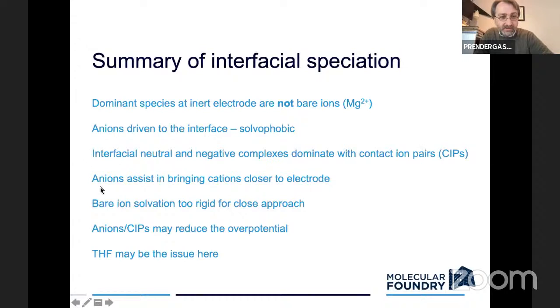But one thing you could draw from this is that the anions themselves are assisting in bringing the cations closer to the electrode, even when the electrode is negatively charged. That was the biggest surprise. Bare ion solvation, so just the solvent, it's too rigid to bring those objects close enough that they might get reduced. And so it could be that the anions that you have in your solution, in your electrolyte, might be very important in terms of reducing the overpotential, meaning the excess potential you have to supply to begin to reduce metal ions above the thermodynamic potential where you'd expect them to become reduced.